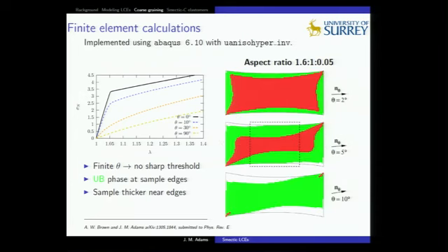But now we can do some more difficult deformations that you can't see analytically. If you stretch at a small angle to the director, then instead of getting the bidirectionally buckled phase throughout the sample, you start to get some of this unidirectional buckled phase at the edges. For larger angles of stretch with respect to the director, you get more and more of this unidirectional buckling phase intruding from the edges. If you eventually go to 90 degrees, then you'll see none of this phase. And mechanically, you see the threshold that we had before start to get diluted as you stretch at an angle to the director.